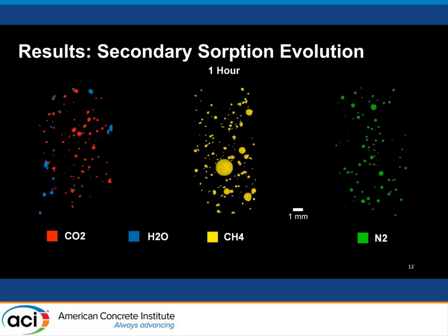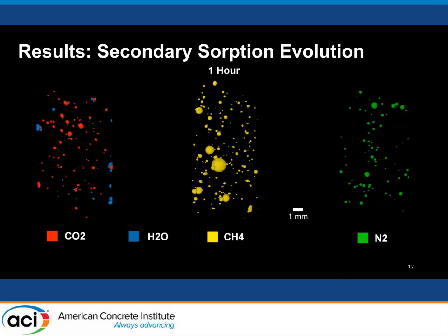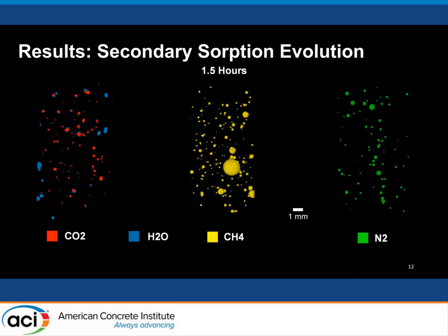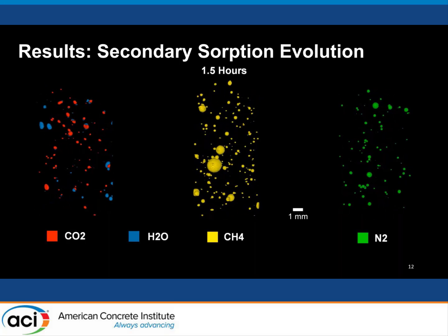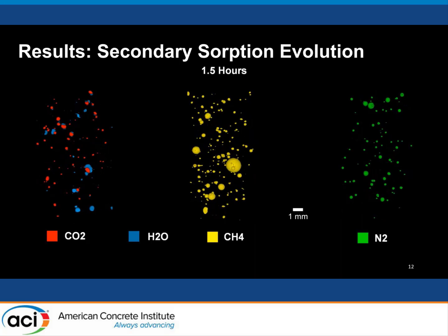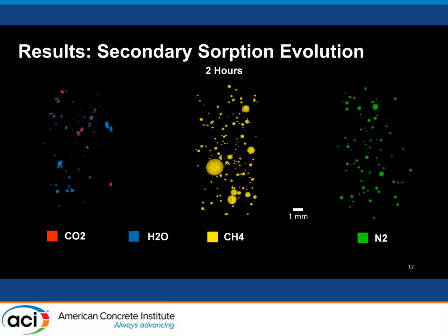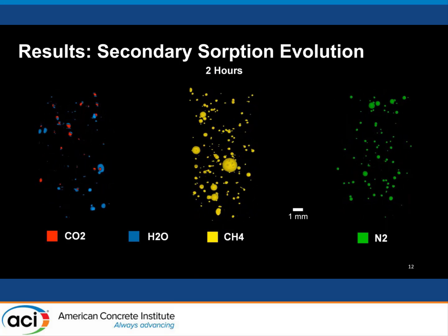And the first observation from this is that within an hour, we saw water advancing into the entrained void system, which, if you remember, the solubility limit is much higher in the CO2 in water compared to that of methane or nitrogen in water.